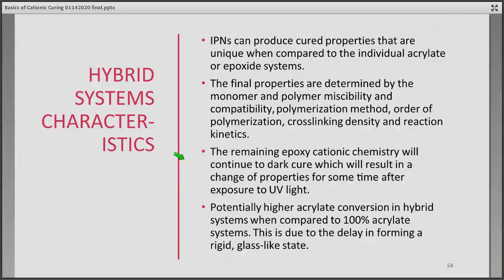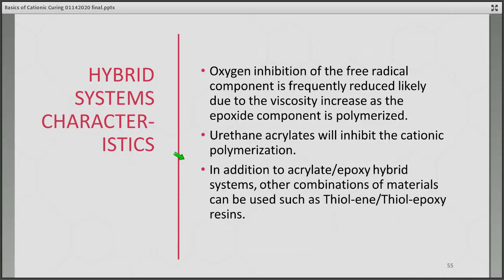You can get potentially higher acrylate conversion in hybrid systems when compared to 100% acrylate systems. With 100% acrylate systems, as they cure, you'll get a very fast formation of the gel or glass state, and that may tend to isolate acrylate bonds. So you may only get curing in what you think is a cured free radical system of maybe 70, 80%. With hybrid systems, you get a much more complete acrylate cure. And this is due to that delay in forming a rigid glass-like state.